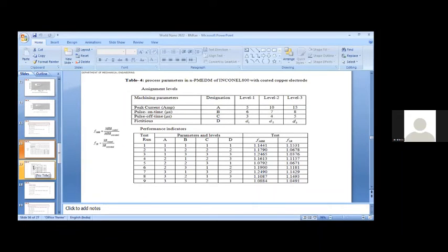Now, when you are doing the earlier one without silver coating, copper electrodes were used. Now, what is the advantage of going for silver coating with the copper electrode? The same experiment with the same levels was repeated. But what we have done, just like nanofluids, how much percentage enhancement is there by adding the nanoparticles to the base fluid? So we are taking the ratio of all the fluid properties with respect to the base fluid.